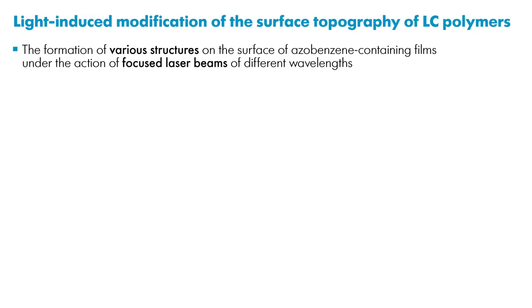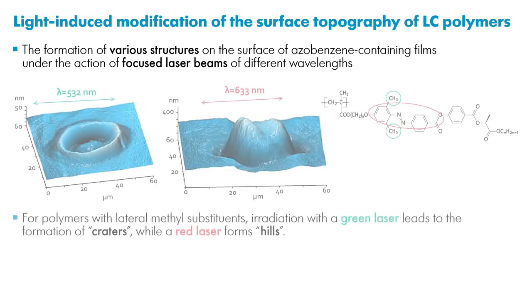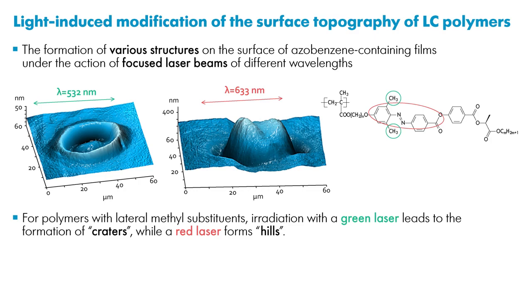The idea is to study the formation of various structures on the surface of films of azobenzene-containing polymers under the action of focused laser beams of different wavelengths. Here you can see the most striking and unusual result of our work. We have studied polymers with azobenzene groups containing lateral methyl substituents. For the first time it was found that irradiation with green laser leads to the formation of craters, while a red laser forms hills.